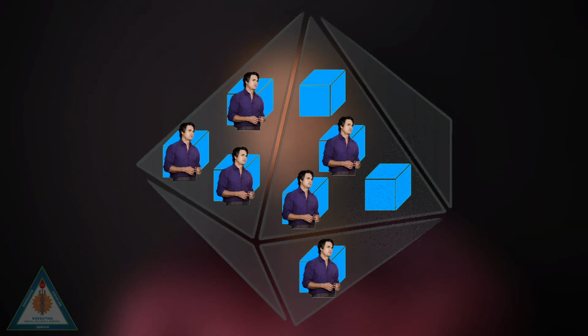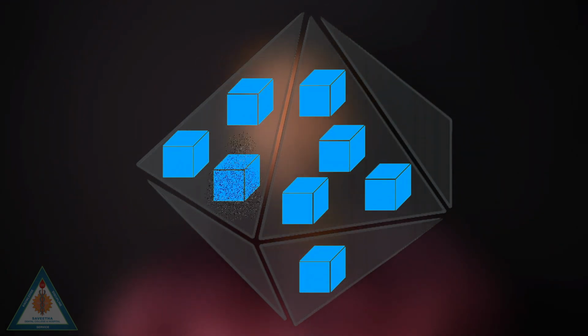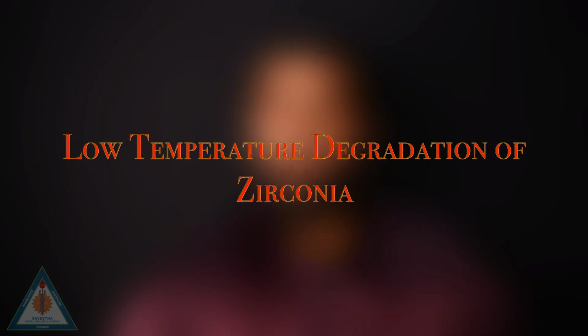The monoclinic crystal is larger, less well arranged and makes for a very haphazard crystal arrangement. However, it is stable at room temperature. Throw in too many crystalline transformations from tetragonal to monoclinic and what happens is a catastrophic destruction of the entire crystal structure. This has been referred to as low temperature degradation of zirconia.